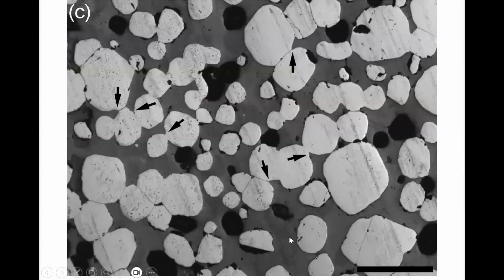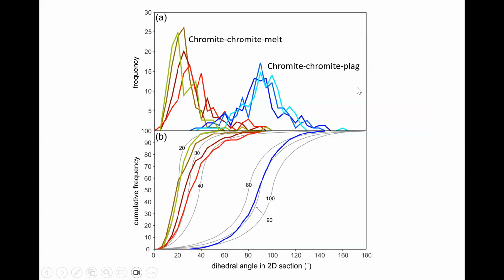So if we look in detail at the UG2, you see that these grains are very, very rounded. Look how beautifully rounded they are. They're really not that faceted at all. And in fact, the last talk set this bit of my talk up very nicely, because if we look at the dihedral angles in here, this is chromite plagioclase. What we see is that it's a much higher dihedral angle. It's no longer down here. It's now up with a nice unimodal distribution around 90 degrees.